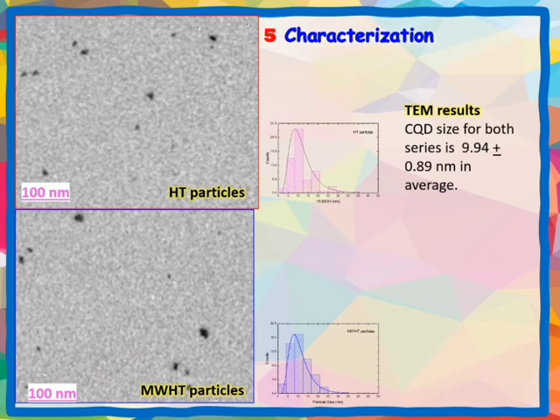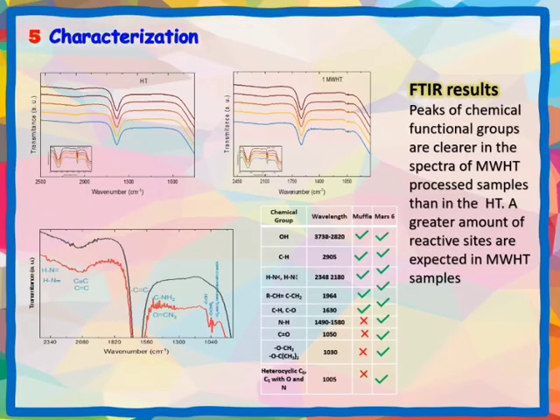These are the Fourier transform infrared spectroscopy spectra. The functional group peaks are observed in greater abundance and more clearly in the spectrum of the samples processed using the microwave-assisted hydrothermal method. It is expected that there will be more sites for functionalizing the quantum dots in these samples.